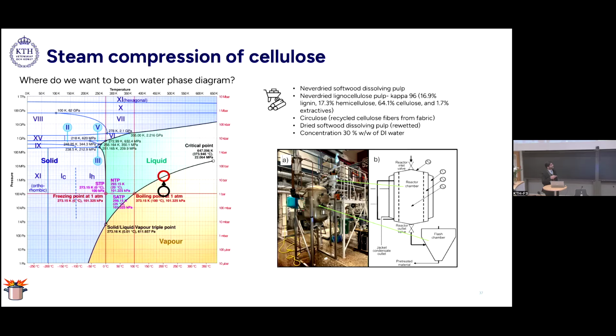And this is the experimental setup where we treat the sample in this experimental reactor. We load the sample from the top, and it is treated with steam for a certain time span, whatever we have decided on. After the experiment, we open a small opening here, and with that valve we quickly and rapidly rush out the sample through a small orifice. All of that is creating the steam pretreatment